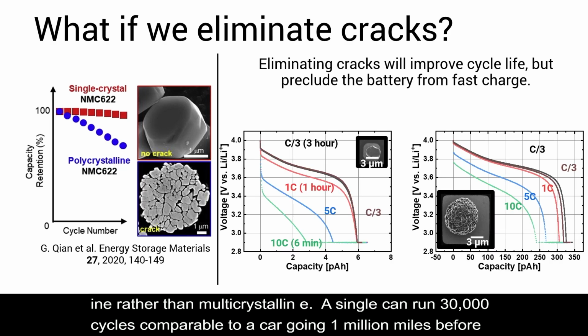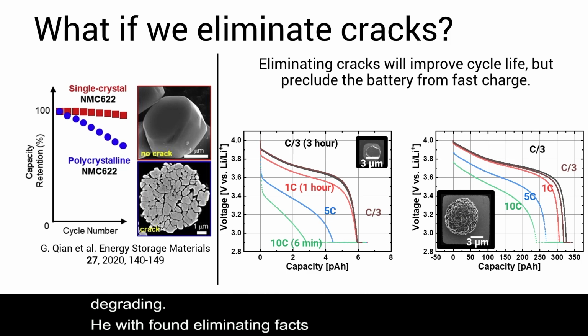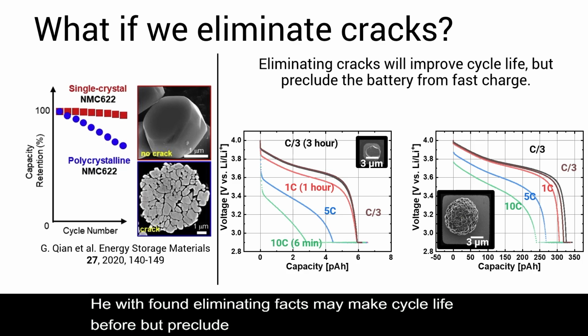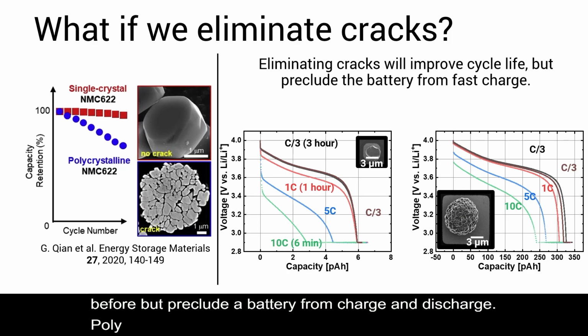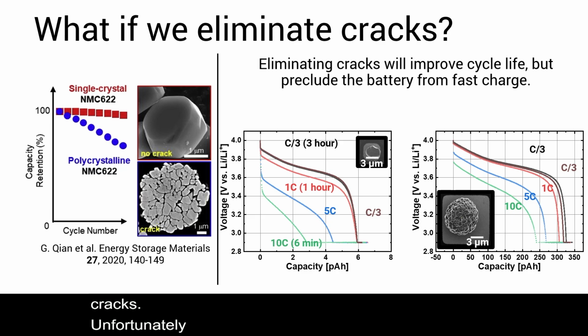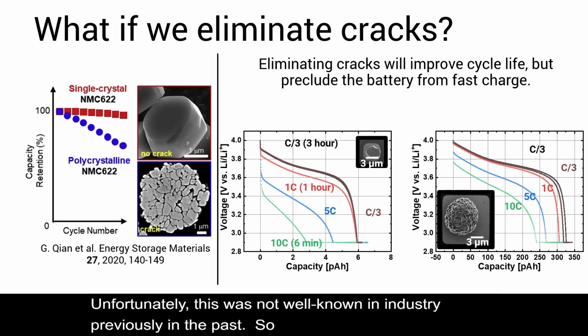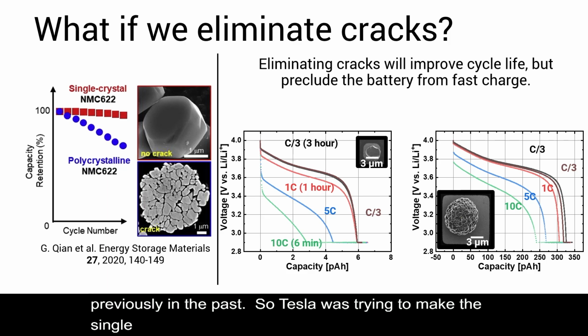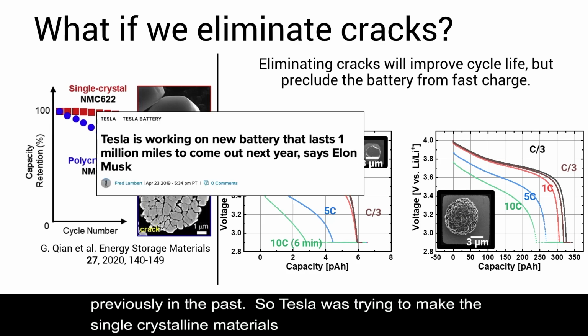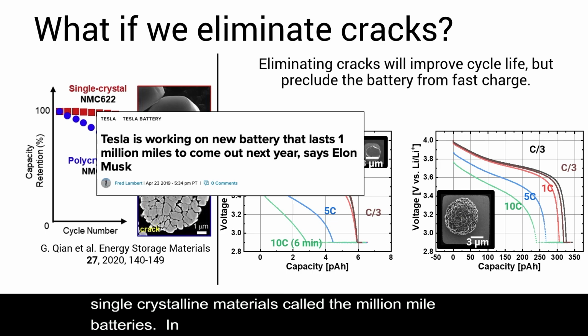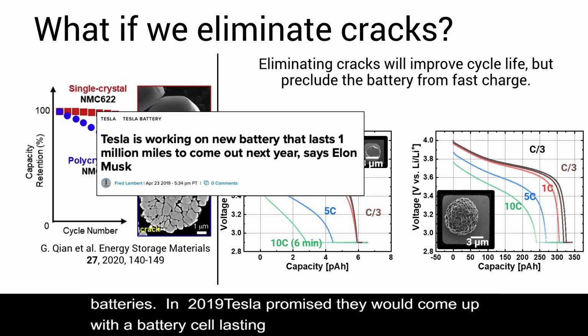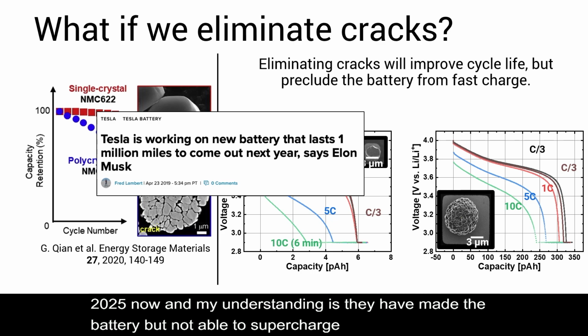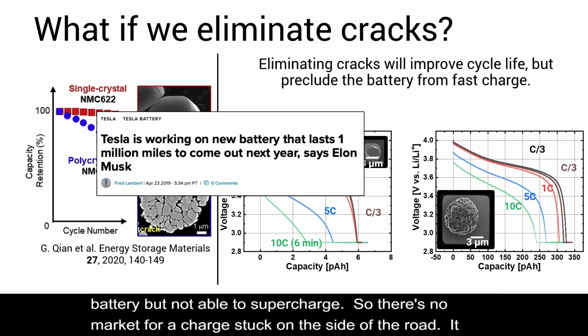What we found is that eliminating cracks will probably make cycle life better, but will preclude the battery from fast charge and discharge. So this is some of our work that shows that polycrystalline particles can be cycled much faster than the single crystalline particles because of these cracks. Unfortunately, this was not very well known in industry in the past. So a couple years ago, Tesla was trying to make these single crystalline materials that can, in principle, last a long time. They call these the million-mile batteries. And you can see in 2019, Tesla promised that they will come up with a battery cell that lasts 1 million miles by the year 2020. So it's 2025 right now, and my understanding is they probably made a cell that lasts 1 million miles, but then they found that it's no longer able to supercharge. So there's no market for a car that cannot supercharge when it's stuck on the side of the road. So it can last 1 million miles, but you won't be able to charge it if you're stuck.